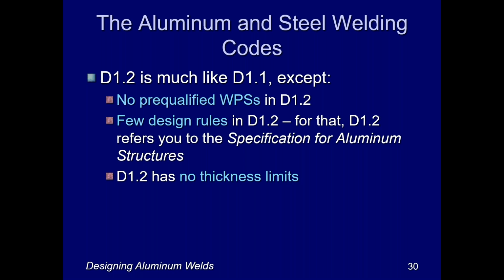There are very few, if virtually no, design rules in D1.2. The nice thing about D1.2, in my view, is that it refers you to the specification for aluminum structures for those design rules. So there's no competing design rule sets in different documents. D1.2 tells you for design, go to the specification for aluminum structures. The other thing is that there are no thickness limits in D1.2, unlike D1.1, which only goes down to a minimum thickness of, I think, something like 3/16.